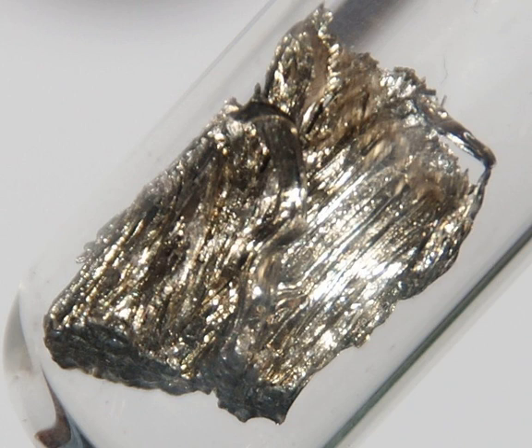Samarium hexaboride. Samarium hexaboride is a typical intermediate valence compound where samarium is present both as Sm2+ and Sm3+ ions at the ratio 3:7. It belongs to a class of Kondo insulators, that is, at high temperatures above 50 K, its properties are typical of a Kondo metal, with metallic electrical conductivity characterized by strong electron scattering, whereas at low temperatures, it behaves as a non-magnetic insulator with a narrow band gap of about 4 to 14 meV.